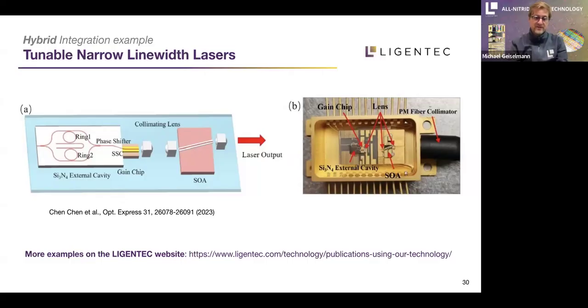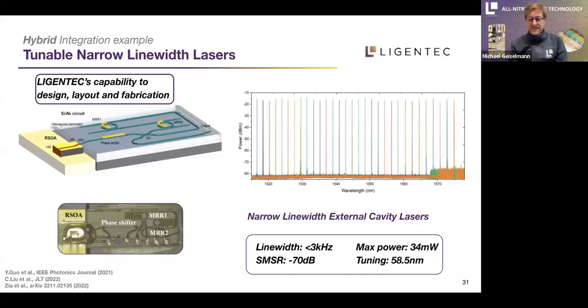nitride circuit, you do a layout of an external cavity laser, and then, for example, with a Vernier effect or other effects which can be found also on our website, we then can get to a laser integration that has two benefits. One benefit is that you get a narrowing of the linewidth of your laser chip. So from megahertz you can go down to single digit kilohertz or below.